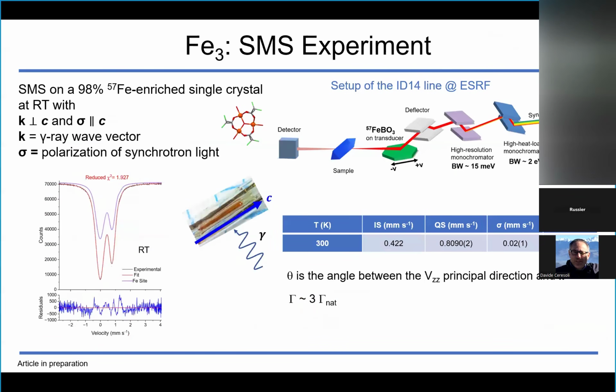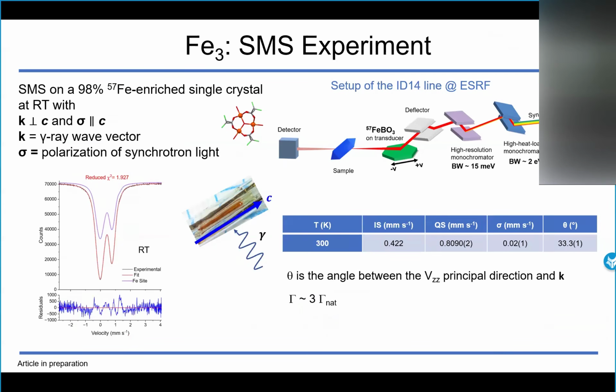Then, as a further test, we measured a Mössbauer spectrum at room temperature of a crystal of this spin triangle. Obviously, because of the better sensitivity needed, we used the synchrotron Mössbauer source, and this is the spectrum taken with the gamma ray wave vector perpendicular to the c-axis and the polarization of the synchrotron light parallel to the c-axis. The values of the hyperfine parameters are in line with those found with the powder, as expected. The spectrum has an enhanced asymmetry with respect to the spectrum of the powder, probably because in this case we are sensing only one orientation and not all the orientations like in the powder.